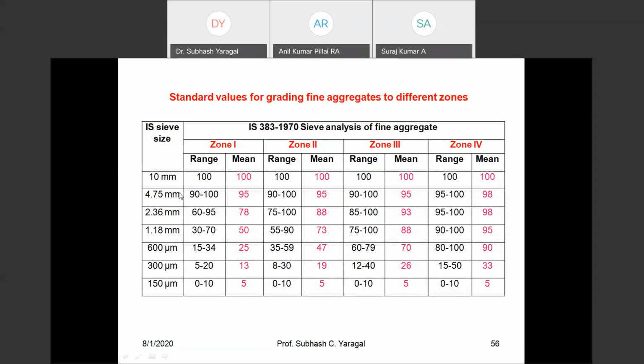So for various sizes, you have the lower class interval and upper class interval, percentage finer, that is given by this code. And for making our lateritic fine aggregate, we have taken the average of the class interval. So if I have to produce zone 1 sand, I'm looking at these percentage finer passing various sizes. If I want zone 2, I'm taking these, zone 3 and zone 4. So we have produced all 4 zones of lateritic sand, and we have also characterized them, and also we have studied the performance in both mortar and concrete.